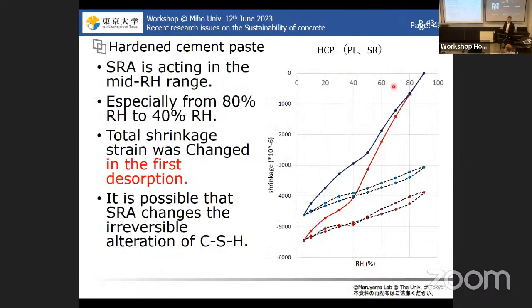But when we do this kind of experiment, the picture is completely different. This is a case of the hardened cement paste. We dry the hardened cement paste at different RH and measure the shrinkage. And this is the normal one, and this is the cement paste containing an SRA. We see that the shrinkage between 80% and 40% differed, or the incremental shrinkage between 80% and 40% changed. But below 40%, we don't see any difference between those.